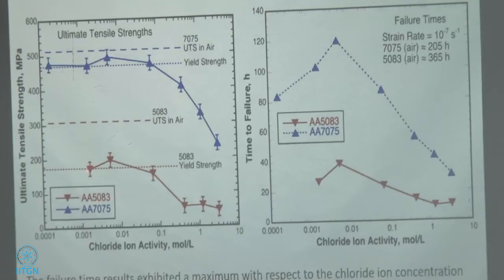Okay. So as the chloride ion concentration gets higher, obviously aluminum alloys do not like chloride ions. It's negative, very bad, right? They don't like it. So the yield stress goes down, the ultimate tensile stress. Okay, but in air, there is my yield stress in air. No problem. Everything is flat line. In air, ultimate tensile stress is flat line. For 70, 75, flat line, yield strength, flat line.